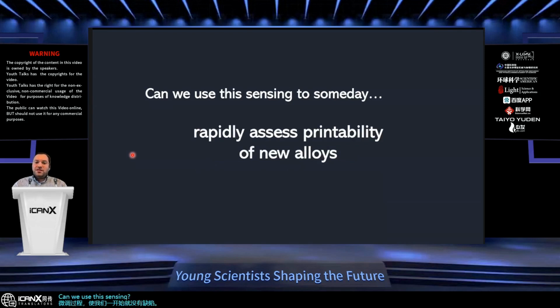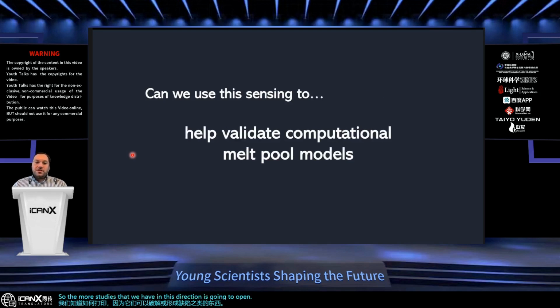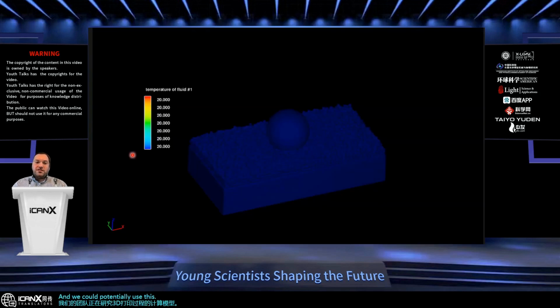Can we use this sensing to assess the printability of new alloys? So currently, there's probably maybe 50 or maybe 100 alloys that could be printed, because out of the 50,000 or so alloys out there, very few of them we know how to print with, because they can crack or form defects and things like that. So the more studies that we have in this direction is going to open the door for printing new alloys. And then our group is working on computational models for the 3D printing process, and we could potentially use this sensing to validate those models.